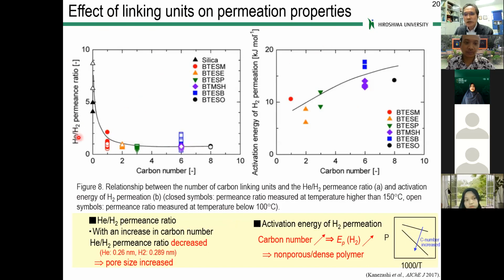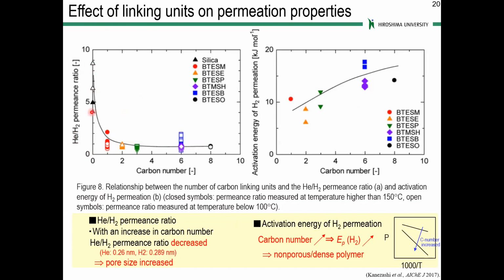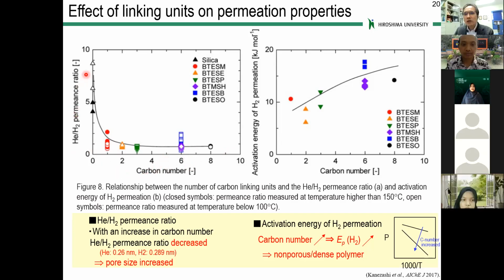Helium over hydrogen: the size of helium is 0.26 nanometer, hydrogen is 0.289 nanometer. So this selectivity indicates the index of the pore size. Higher selectivity indicates small pores. Smaller selectivity indicates larger pores. As you can see, with the increase in the carbon number, the permeance ratio decreased, right? So this indicates pore size increased.